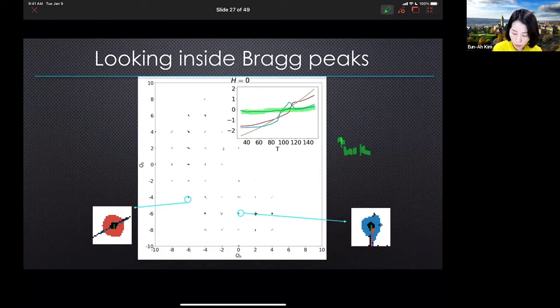However, the diffuse region surrounding the Bragg peaks was separated into two different types of clusters. One of them, the red cluster, is right here. This is the red cluster, which shows heightened intensity all throughout phase two. And this blue cluster had relatively weak intensity in phase two, and it turns on in the lower temperature phase. When I first reported this result to my colleagues at Argonne National Lab, they had difficulty believing it. It was very unintuitive, very unusual. People were not used to thinking about the diffuse region around a Bragg peak having different temperature dependence compared to the center of the peak. What is this? Where is this coming from?